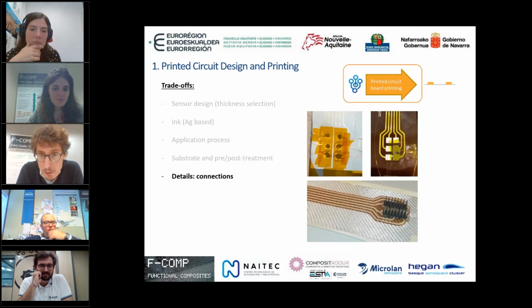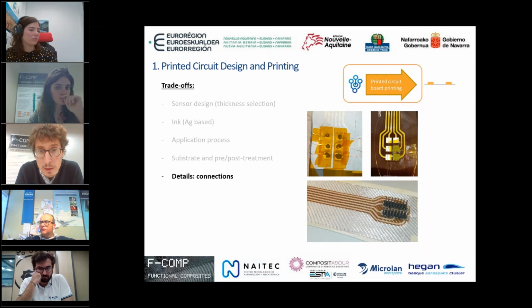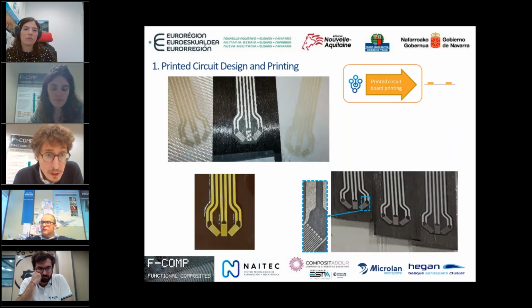We found as well during the project that we needed to define some details like the connections, because some points had not been as good as we wanted, and we finally needed to look for a solution. You can see in the image, just with adhesive glue, conductive glue, putting some connectors. We needed to make some kind of details that later on we further explain. We finished with a batch of almost 200 samples of different materials. You can see in the image at the top.